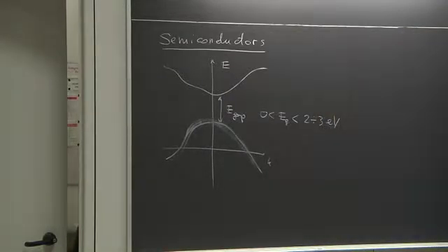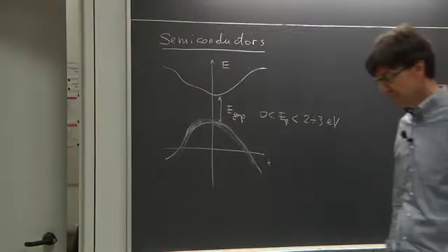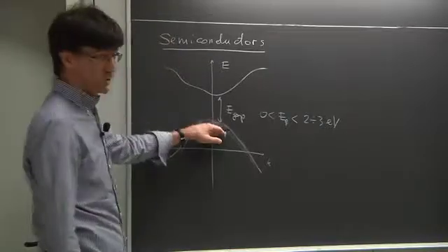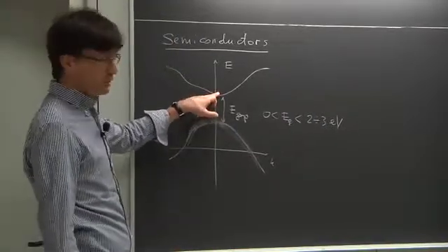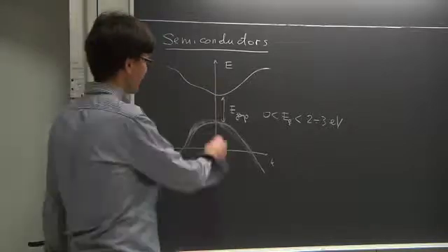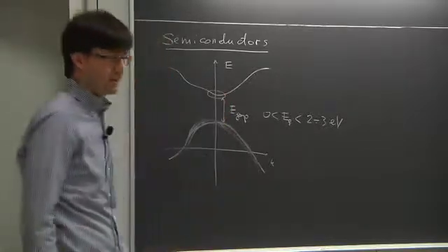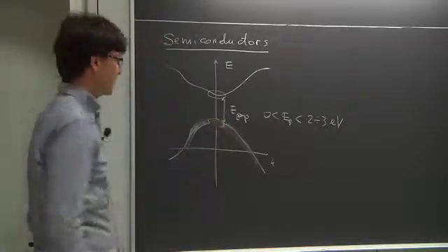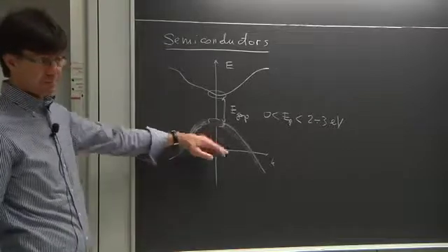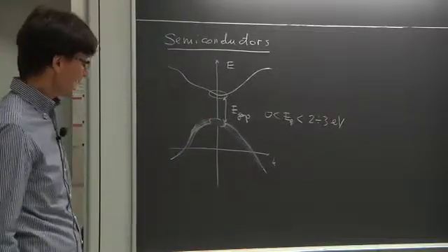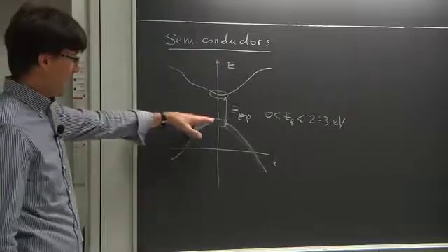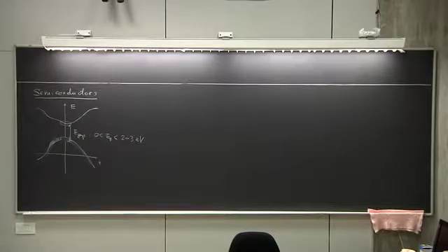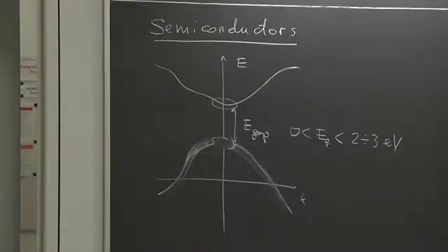And the fact that the gap is small has a number of consequences. The main one being that at finite temperature, there will be a small but finite number of electrons that are excited in this band. And of course, there will be a depletion, right? An absence of electrons in the higher occupied band that at t equals to 0 formally would be completely filled.